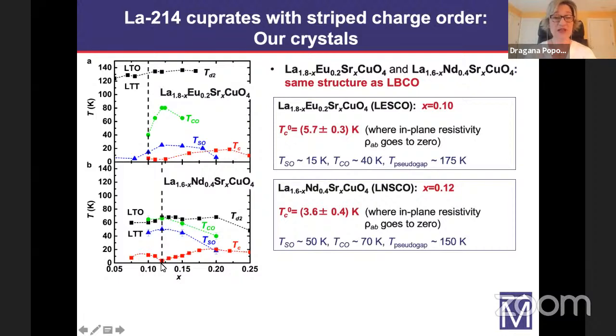LNSCO was at 12% doping, or 1/8. So here TC was very low. You can see it's very suppressed, down to less than 4 Kelvin. And by the way, we define TC as the temperature where the in-plane resistivity goes to 0, or in other words, where it falls below the experimental noise floor. In LESCO, the doping was somewhat lower, 10%. So here the stripe correlations are weaker and TC is somewhat higher. These TCs are much lower than the temperatures where stripes are established, and they're also much lower than the pseudogap temperatures for these materials.